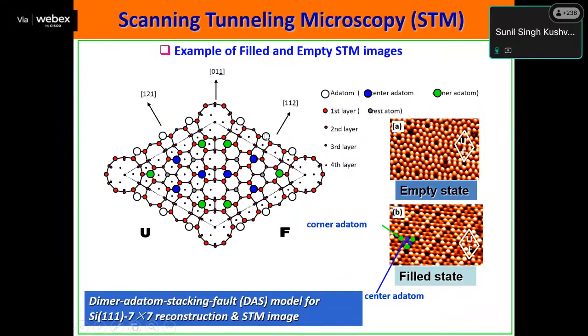So for example, here we can see this is the well-known silicon 111 7x7 structure. This is one of the models people have proposed, so that they can have this 7x7 reconstruction. They have the dimer adatom stacking fault, that is the DAS model. So again, as I mentioned, in UHV you are able to see it, or even check whether your STM is working properly or not. 99% of people use this silicon 111 7x7 reconstruction. It is again the same story.